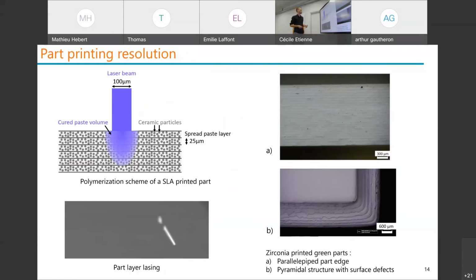And to make you understand a bit more, I can show you the scheme of the cured paste volume. So you can expect a different shape, bigger on the side of the laser beam and less depth when you have more diffraction and also more absorption. So you lose in resolution, as we lost here. You can see on the right when the shape is a bit different from something rough. You can see that we didn't manage to be very precise because of a gradient of polymerization. So it's small layers that are a bit polymerized, but so polymerized that you can't remove them, but not so much. So you will have defects on this side and you won't have the shape you want.